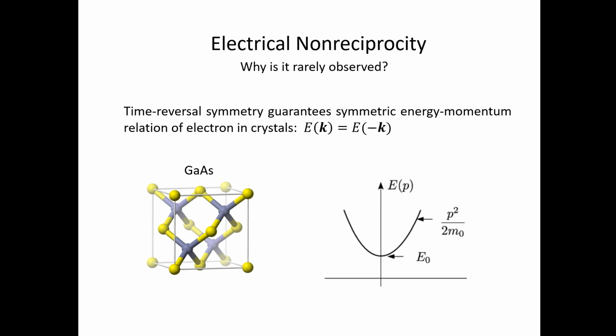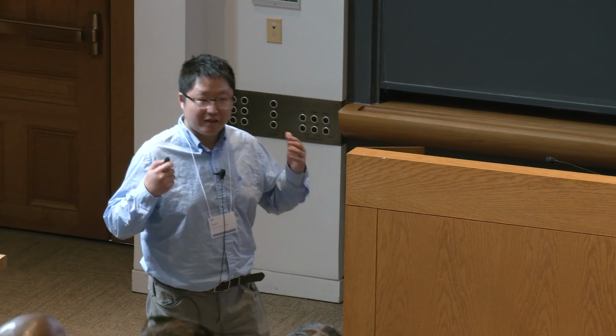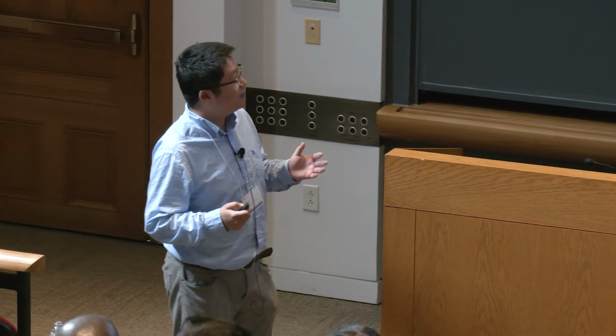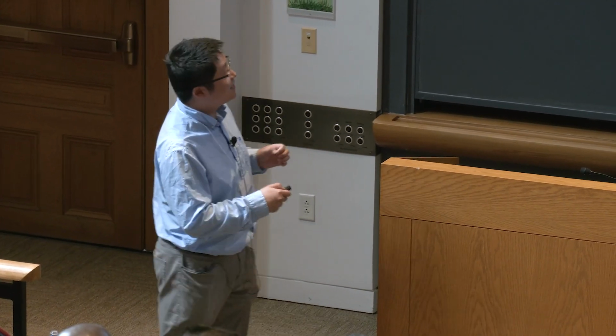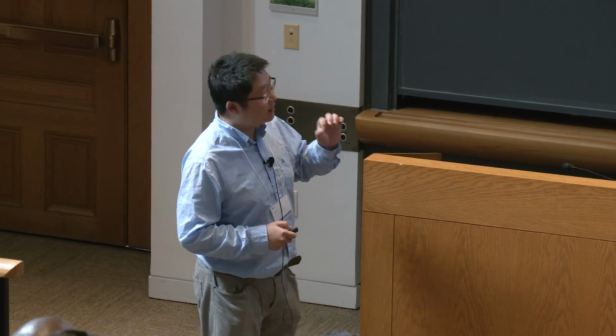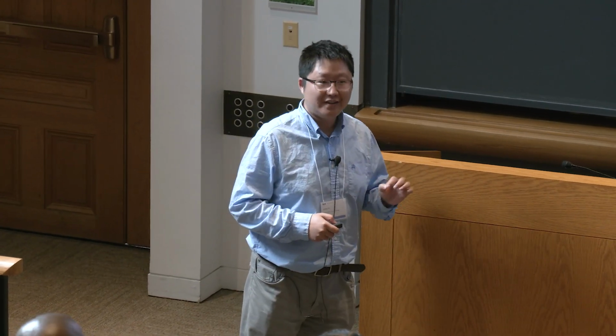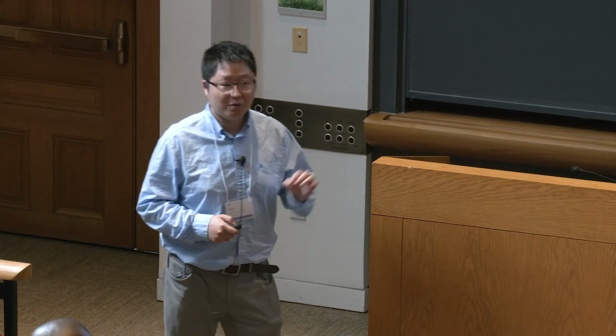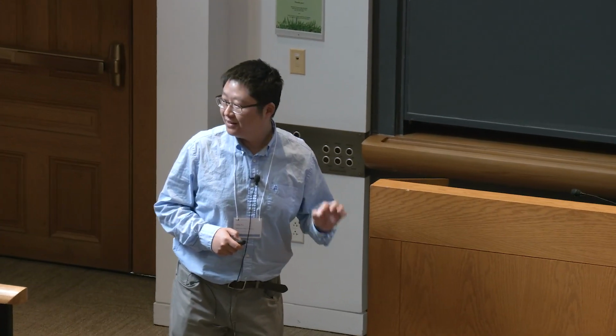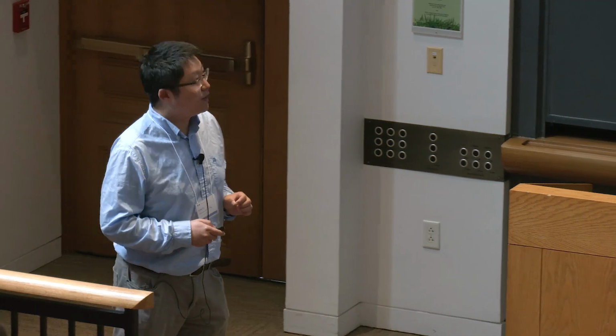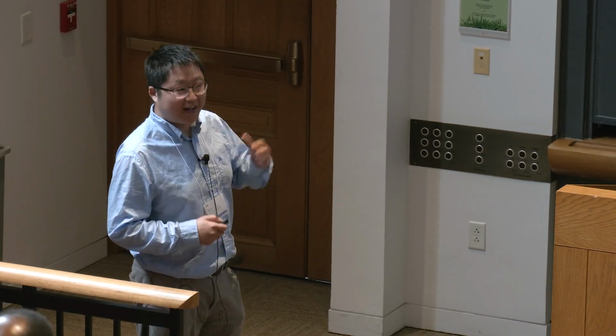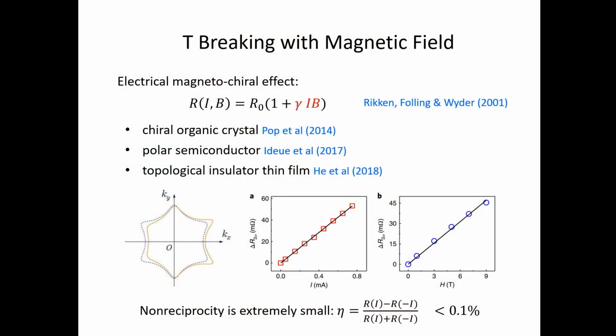The transport theory of solids traditionally is based on the energy momentum relation. Therefore, under the condition of time reversal symmetry, meaning in non-magnetic materials, even if inversion symmetry is broken, as is the case in gallium arsenide, the symmetric energy momentum dispersion leads to the absence of non-reciprocal effects in the conventional transport theory. So really, to go beyond this standard theory, one has to think about various ways to either break the time reversal symmetry or to go beyond the conventional transport theory. And that's what I'm going to describe.